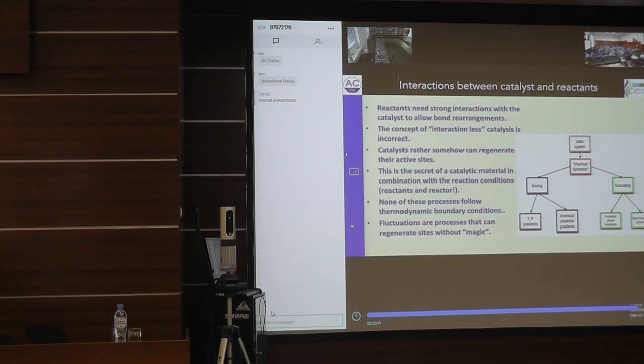One has chemical dynamics that is introduced by forcing, and that means you have to have a gradient in temperature or pressure, or in chemical potential more generally. That is usually the case in a flowing reactor, because in a flowing reactor you have gradients of everything that controls the local chemical potential. Or you have a truly fluctuating situation in which you are in the state of a so-called first-order phase transition. And then you exchange the ligands between the surface and the bulk, and the surface and the gas phase. So an adsorption-desorption equilibrium, for example, would be such a situation.